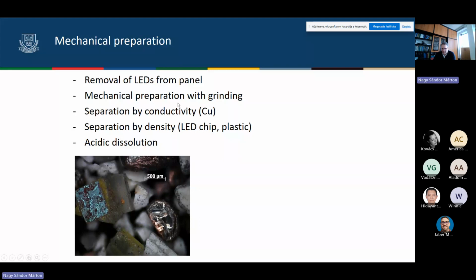Mechanical preparation with grinding. We started with grinding to liberate the different parts of the LED. After that, we made a separation by conductivity. It means by electrostatic equipment, we were able to remove the copper part. It's quite a large amount, the copper part of these LEDs. It's important to insert the voltage or electricity into the LED. And with the separation by density, we were able to separate the LED chip from the plastic parts.